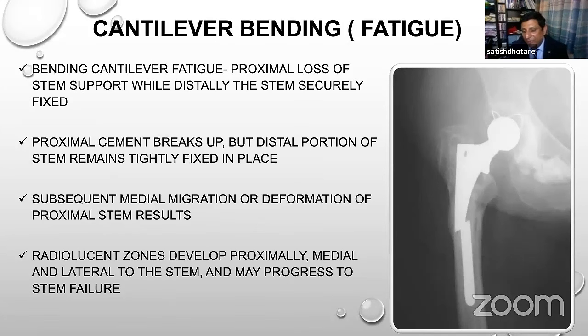Now, cantilever bend, and I have seen quite a few cases of cantilever bend. What does cantilever bend mean? It means the stem is well fixed distally, and there is some loosening around the proximal end. Either there is a breakage of the cement mantle, or there is osteolysis causing no support in the proximal aspect of the stem. Because of that, continuous load leads to deformation, which results in breakage at the area of more fatigue and more stress. That's why these stems fail with fractures. And you'll be surprised how well fixed this distal stem is, because I've seen some of these cases so well fixed that we had to do an osteotomy to remove it. It's very difficult to remove those well fixed distal portions of the stem, and that is cantilever bend.